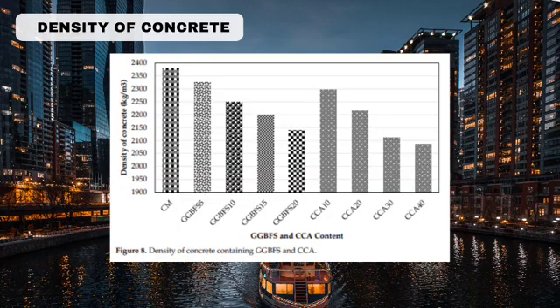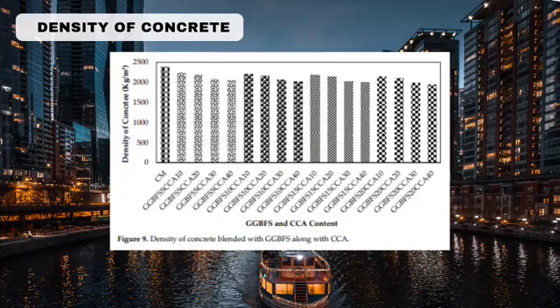decreases. Also, the density of concrete is calculated as 2,378 kg/m³ in the concrete mixture made of PC only, and the lowest density is 1,935 kg/m³ with GGBFS 20% and CCA 40% as a PC and fine aggregate replacement at 28 days. The outcome shows that enhancing the combined use of GGBFS by the weight of PC and replacing FA with CCA in the mixture plummets the density of concrete.